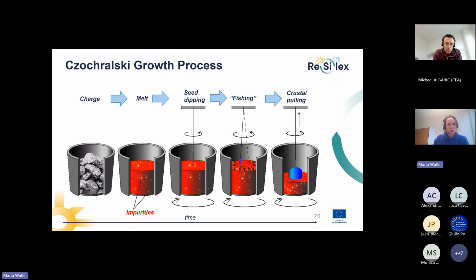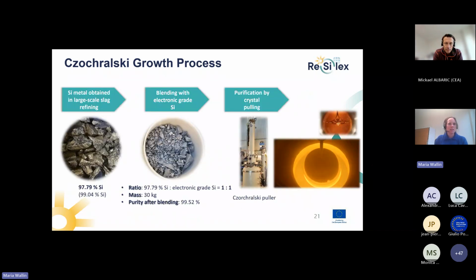And that's why we also tried this other Czochralski process. And the difference here is that you charge it here as well, impurities, and then you dip the seed and you rotate the crucible. And then first we did some fishing to get rid of the impurities. You can see on top here, it's floating on top. So we tried to fish it up and remove the top part. And then we started to pull our crystal. You can see the pulling process.